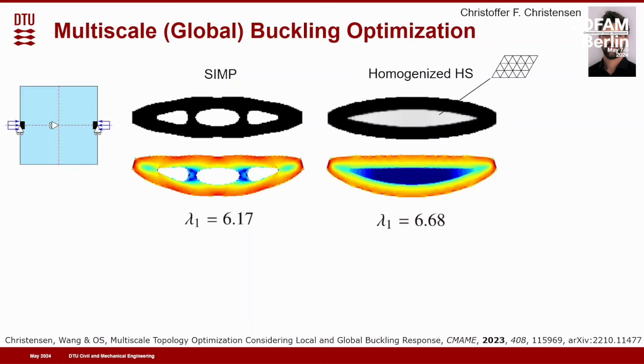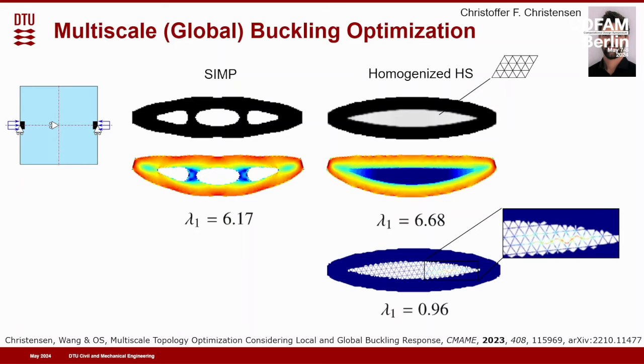Then we get a slightly higher buckling load. So that's nice. That motivates, hey, there is actually need for lattice structuring here. But if we dehomogenize that, so we actually realize this structure by making the full analysis of it, it turns out that it's buckling, it's getting unstable in the lattice structure. So in this case here, we didn't gain anything from latticing again.